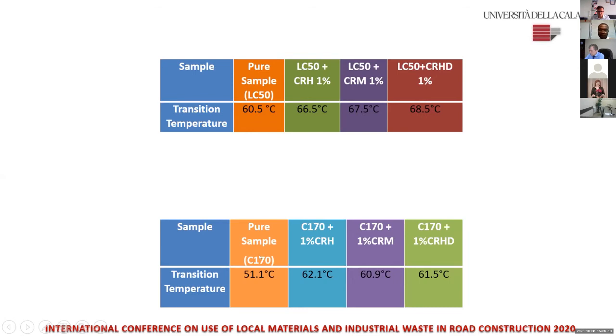For the second bitumen, C170 with a penetration grade of 170 to 210, we had a transition temperature of 51 degrees. When we modified it with the additive, we saw 62 degrees, and here 60 degrees, and here 61 degrees, which shows that the additive also improved the rheological profile, the rheological characteristics, of both bitumen samples.